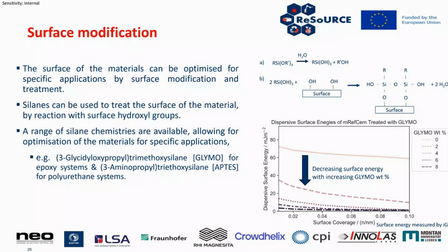From this size reduced, we can also surface modify these materials. So we can use compounds like silanes to treat the surface, to change the surface energies, which allows tailoring of the surface energy of the material to incorporate better into different polymer systems. For example, you can use this GLYMO to incorporate better into epoxies, or an APTES into a polyurethane.